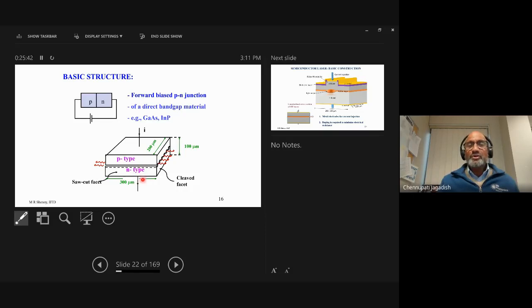For the N-type semiconductor, you dope with silicon typically, or tin. Silicon is from group 4 of the periodic table, so it replaces gallium or indium, and it has an excess electron. That's where you get the negative, N-type semiconductor. These two have a metallurgical contact between them, where you deposit one on top of the other with different dopants, and then you're able to make a PN junction. Then you make contacts, inject current, and look at the light coming out. The facets you create, the crystal or cleaved facets, will also play an important role, which I will come back to. Again, lasers and LEDs are forward biased, because the P-type is connected to the positive terminal and the N-type is connected to the negative terminal.